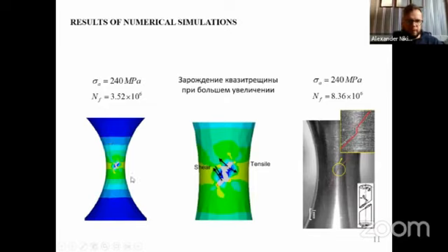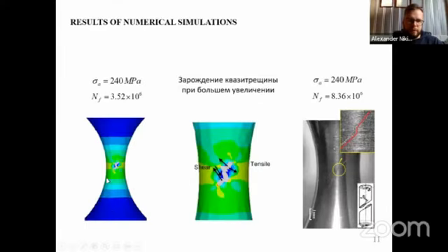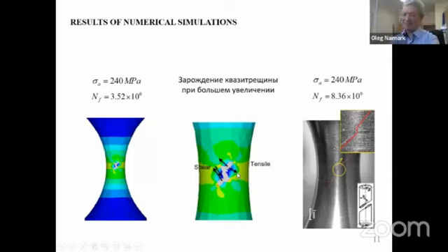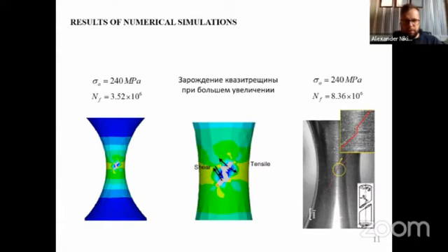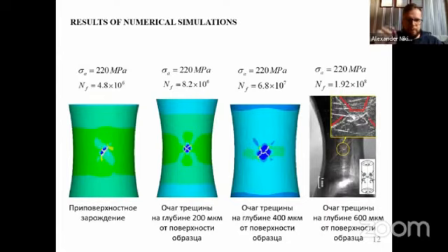We use ANSYS for calculating the stress state. We can make the calculation in an elastic assumption or elastic-plastic. Elastic-plastic is very long, so here I present just the elastic solution. We calculate the stress state with ANSYS, then apply our algorithm to calculate the damage function, and use the kinetic equation to describe the evolution of damage. Alexander, I am sorry, time is short. Okay, here the green color represents the quasi-crack. We get the crack initiation from the surface, and after we put an additional hard element inside, deeper and deeper, we get the X-type crack with two perpendicular cracks.